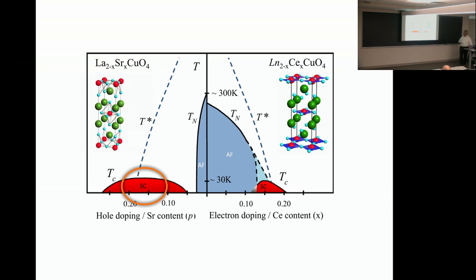And what is going on there? In fact, the puzzle really is that if you go beyond this, say, around 19-20% doping out here, then many of the properties, electronic properties that you measure by STM, by photoemission, and so on, completely fit the band theory. So if you give this crystal structure to a band theorist and ask them to work out what's going on, they will get almost everything right. On the other hand, below this dashed line here, if you try to compare the electronic properties of the normal state or even the superconducting state to band theory, they just fail completely.